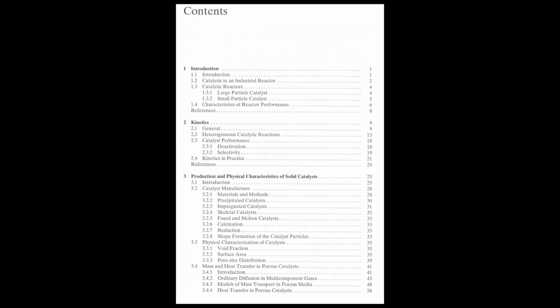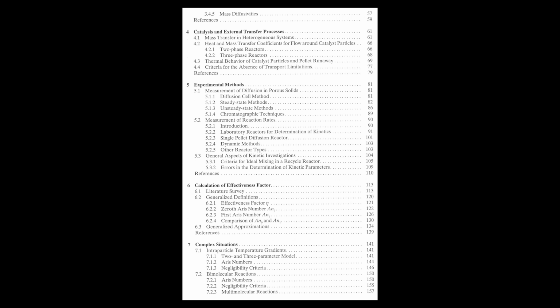For reactions that release heat, those exothermic ones we mentioned, the temperature inside the catalyst pellet can become significantly higher than the temperature of the surrounding bulk fluid. This happens because the heat is generated inside the pellet where the reaction occurs, and it takes time for that heat to conduct out to the surface and then transfer to the fluid. So the inside gets hotter than the outside. Potentially, yes. This temperature difference can, in turn,